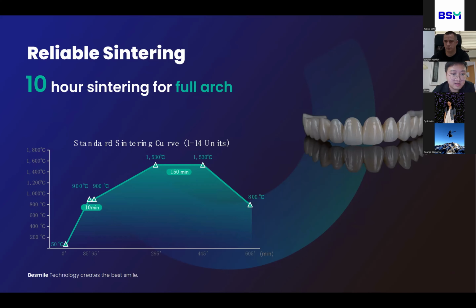And the curve here is the standard sintering curve for our 3D Master. You can see totally 605 minutes. And there are 2 stages, 900 degrees holding 10 minutes and 1530 degrees holding 150 minutes. And this curve works for the restorations from 1 unit, single unit, to 14 units.